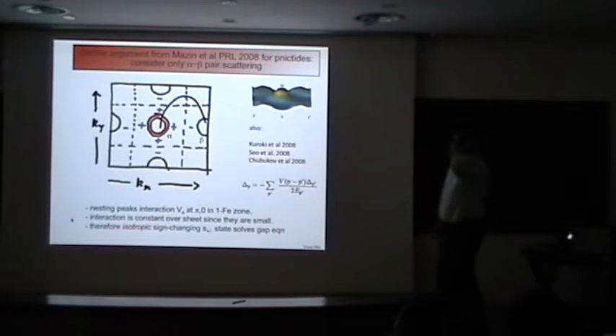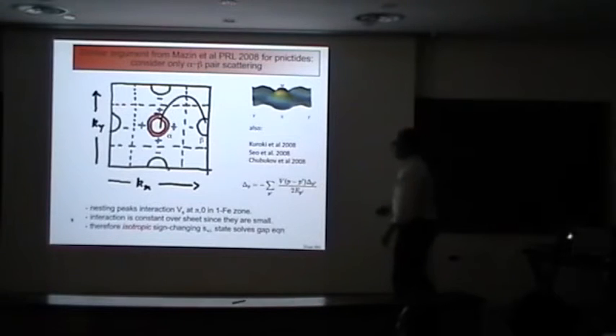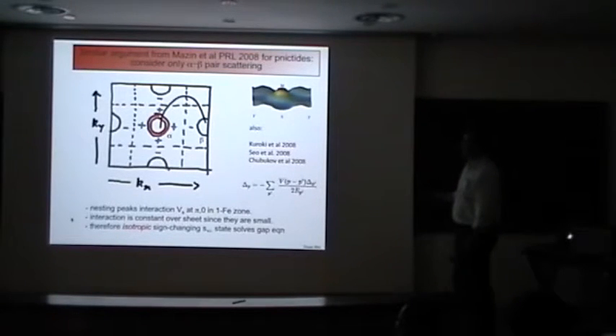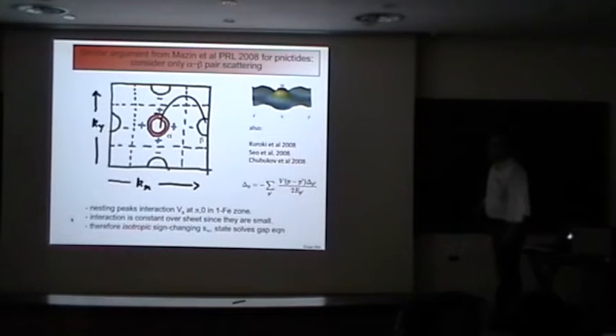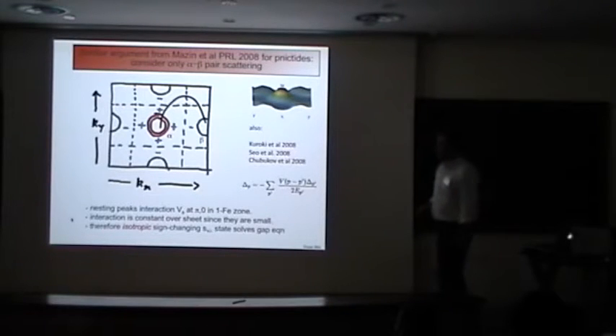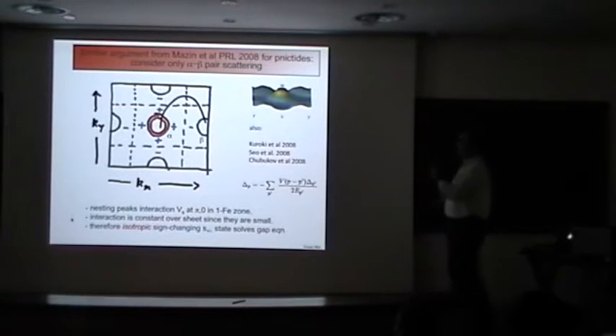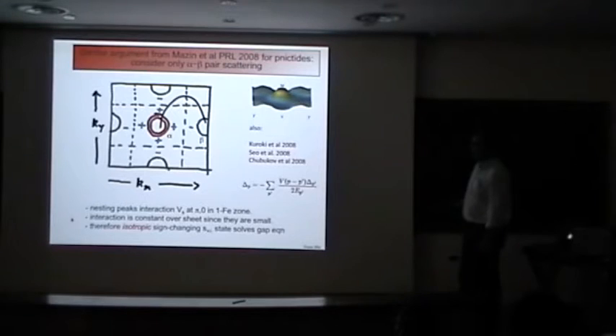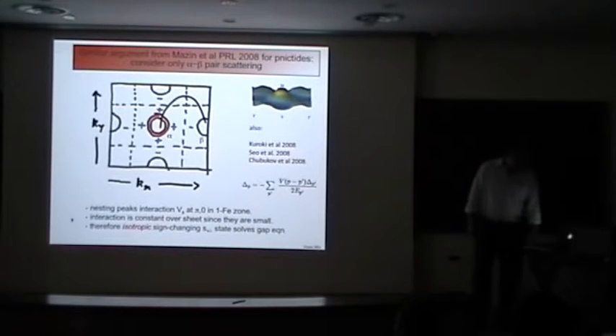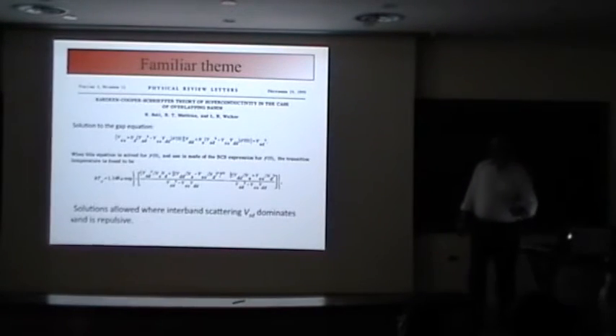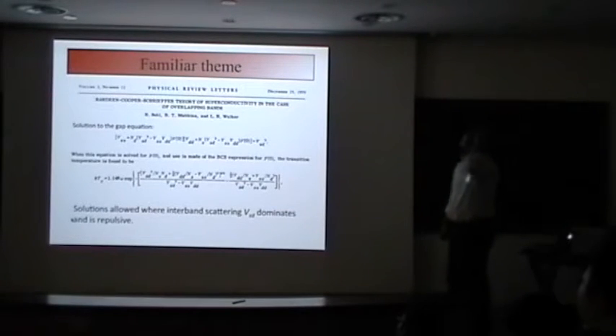So this is what Igor pointed out in 2008 for the pnictides, that type of repulsive interaction would just give you, since these Fermi surfaces are not too big, one sign of a gap on the hole pockets and another sign on the electron pockets. That would just be the S plus minus type pairing, which has been followed up by many different people, and this band-band scattering can give you this S plus minus state.